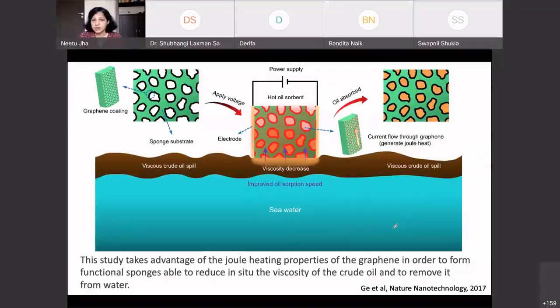So another thing where nanostructured materials have come to the rescue is this area where viscosity of oil is a major problem. So what you can do is make a sponge, or coat graphene on the sponge, and then this graphene absorbs the oil from the surface. Now graphene is hydrophobic in nature, so it does not take water into it, but only oil. And then these pores are completely filled with the oil, and later on you can remove this oil and use it. So that is one area.